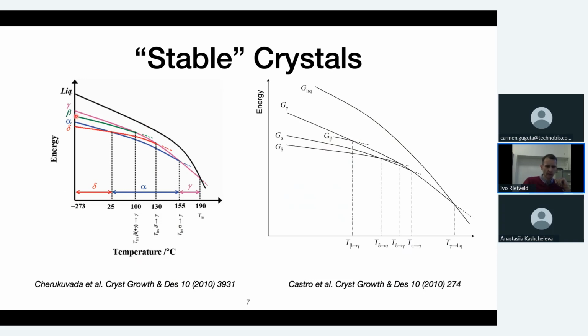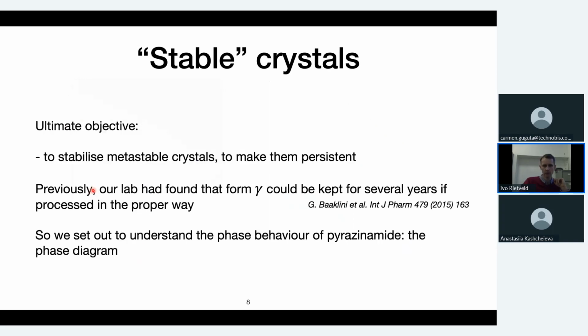Here you can see the beta form, which is kind of slightly below gamma, and you can see this in this phase diagram also, where the beta form is kind of floating high in among the forms, and definitely not considered to be a stable form, more delta than alpha again. And so what they clearly agree about is gamma is the high temperature form, alpha intermediate, and delta then the low temperature form. Well, that idea, in a sense, I'm not going to change, but we are going to add a few details to these phase diagrams. Just to explain why bother if you, in a sense, already have this information.